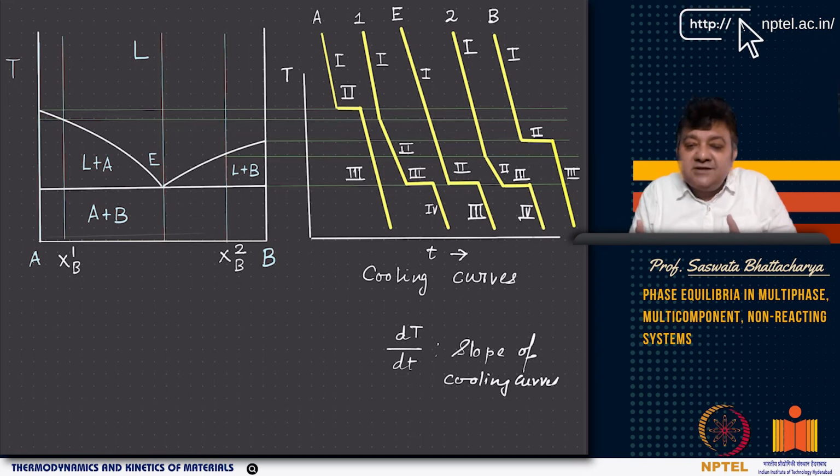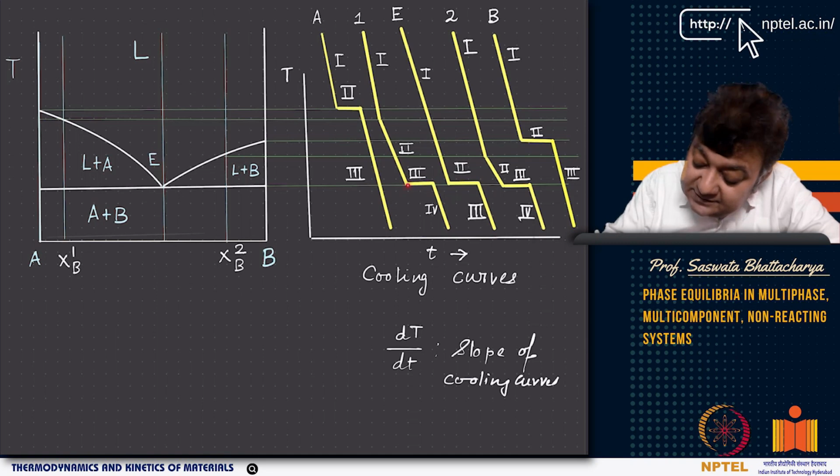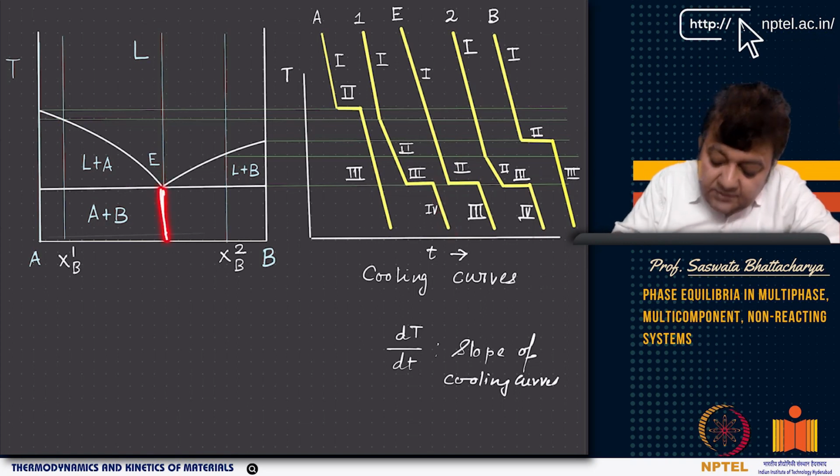This heat evolution is now balancing the heat released by the furnace during cooling. The heat released by the furnace during cooling is now balanced by the heat involved as a process of this eutectic freezing at E. And that is why you get this horizontal line 3, and then once you just cross the eutectic point, again you have a drop in accordance with the conductivity of the solid, the entire solid mixture.